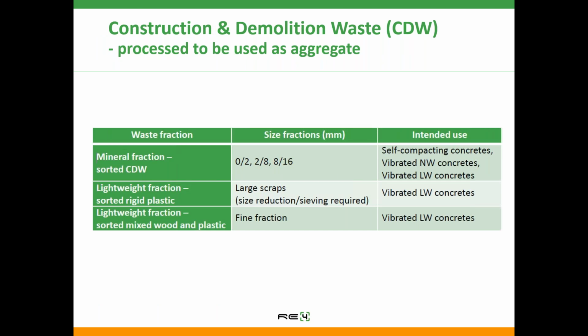Construction and demolition waste is an inert fraction, and it has to be processed before it can be used as aggregate. So the mineral fraction was sorted into fine aggregate, 0 to 2 millimeter, and then two sizes of coarse aggregate, 2 to 8 millimeters and 8 to 16 millimeters. They were used for self-compacting concretes and vibrated concretes. The lightweight fraction was the rigid plastic that required sieving because of the large particles, and we also used mixed wood and plastic as fine fraction.